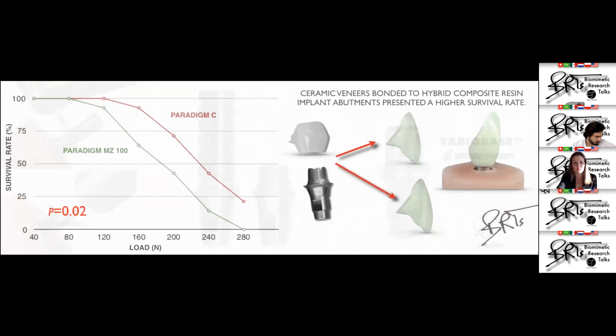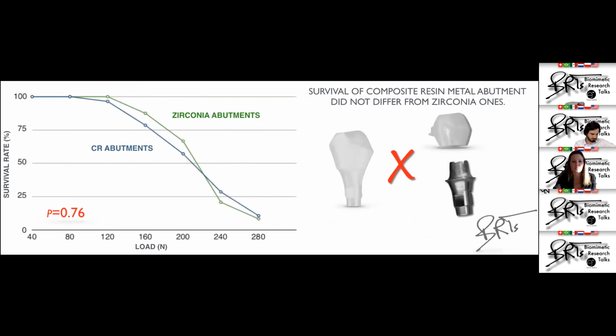According to our results, we figured out that Paradigm bonded to hybrid composite resin metal abutments presented a higher survival curve, around 21%. And all the samples with composite resin in composite resin metal abutments had broken. And when we pooled the data from Maria's study and our study, we saw that both abutments had a similar performance on this accelerated fatigue test. Those abutments have the same performance.